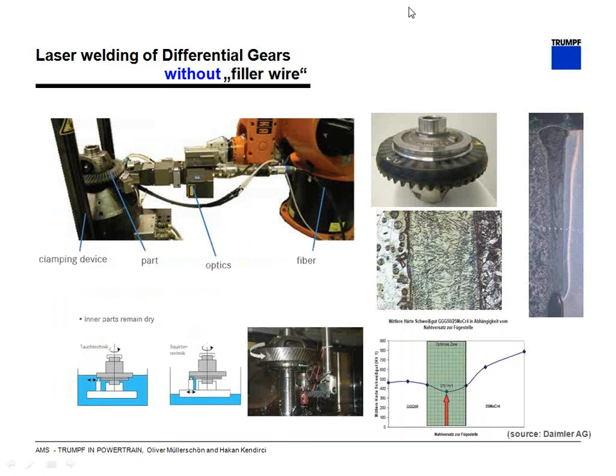This is an example from Daimler on that slide here. You can see it's in mass production, welding without filler wire of these two joining partners. You can see the part itself here, and a very thin and narrow welding seam here on the right side, made without filler wire. The welding speed itself is up to 3 times higher compared with the conventional laser welding process with wire.